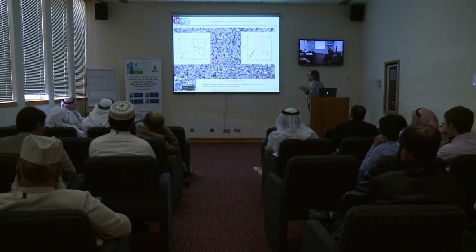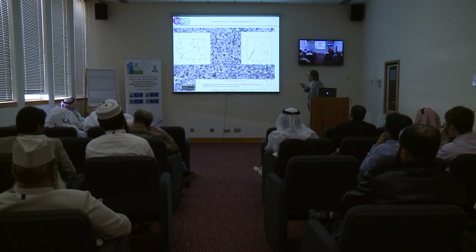So you can have this particular spectrum. This is the first one that was reported, a 45 degree line. This is electron diffusion around here, okay? And then here we have capacitance and charge transfer resistance, which are here. And then sometimes you have more things, one, two, three arcs.